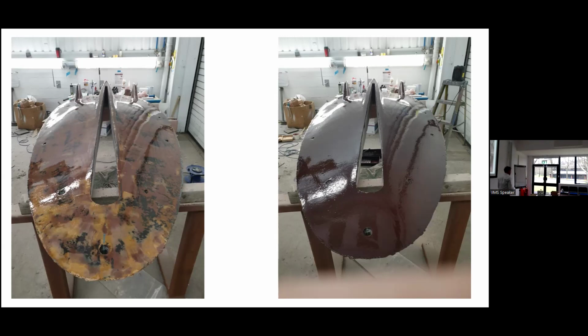So the clue to getting good adhesion is to use the product with the maximum adhesion, and that will be the lower viscosity resin hardener. So that was brushed on. I used a brush for this, so it was nice and easy to get a lot on. All the runs just occurred at the edges.